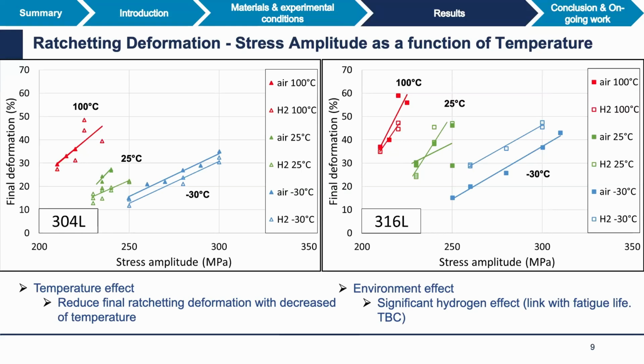So in these graphs, you have the variation of this final deformation as a function of temperature for the two environments. On the left-hand side for the 304L, and on the right-hand side the 316L. So as expected, the progressive deformation is higher at elevated temperature than at low temperature. But it's difficult to interpret because, of course, you need a higher stress also at this temperature.